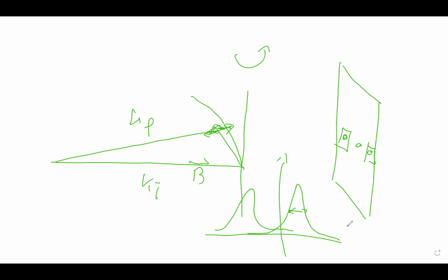And I was just wondering if you check the textbooks for small-angle scattering, where you have the correlation length along the beam. So let's say this is the Z direction. And then you say, okay, the correlation length along Z is lambda squared over delta lambda, which is around 10 nanometers. And this does not correspond at all to the very long correlation lengths you can extract from your experiments, and that's real, of course. So I was wondering if we can work out why this is the case.